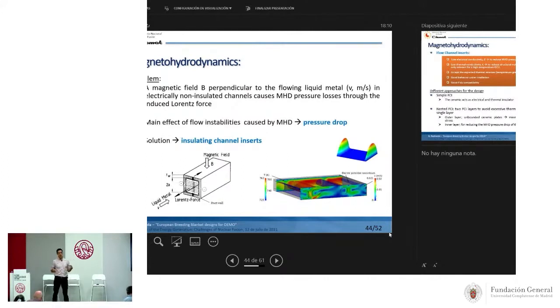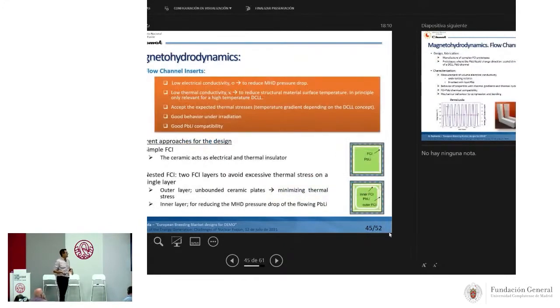And the solution that was found in the past 20 years ago to solve or to mitigate this problem is the introduction of insulating channel inserts. These flow channel inserts have these main requirements. The first one is to have a low electrical conductivity, to have low thermal conductivity, to accept high thermal stresses, and of course to present a good behavior under irradiation.